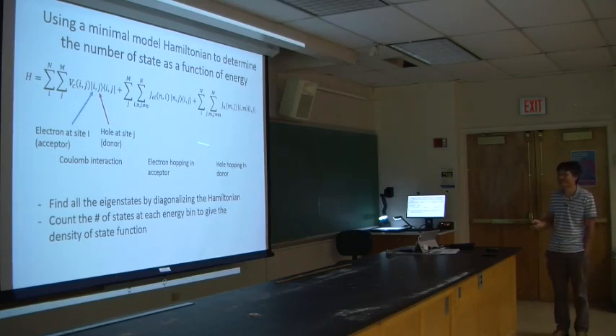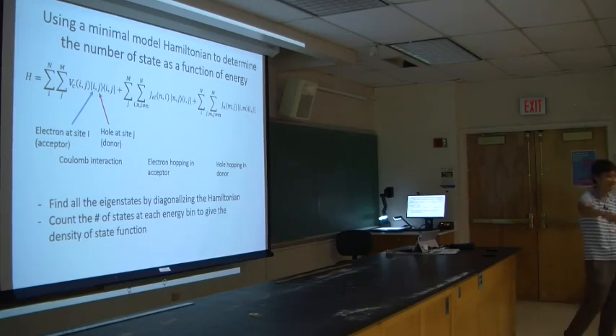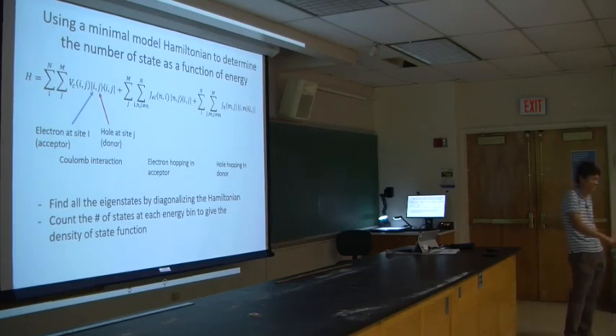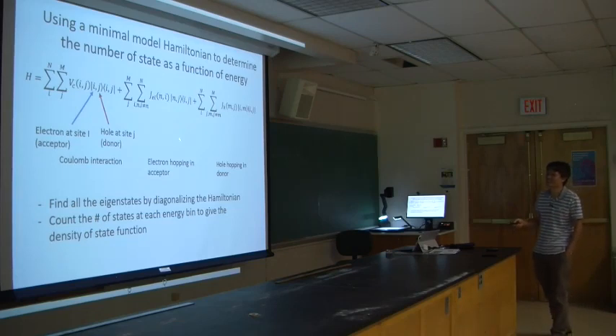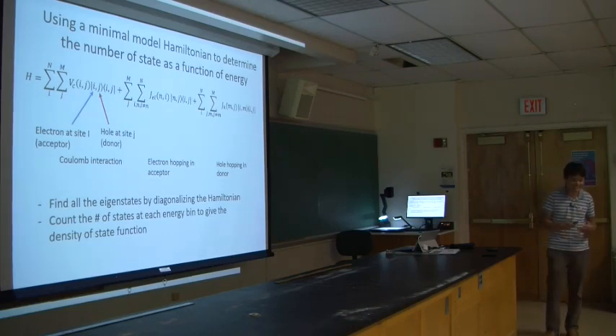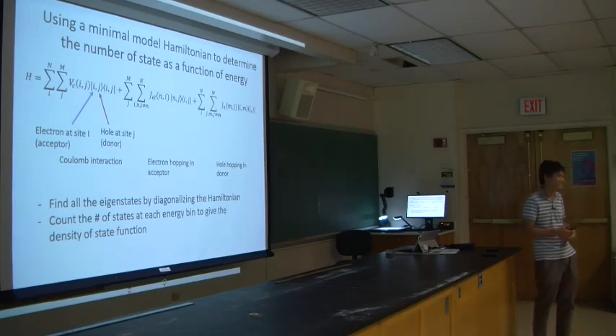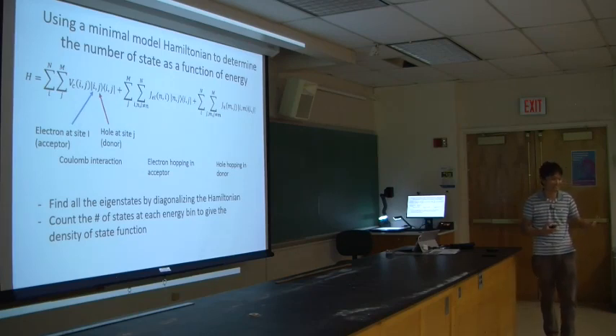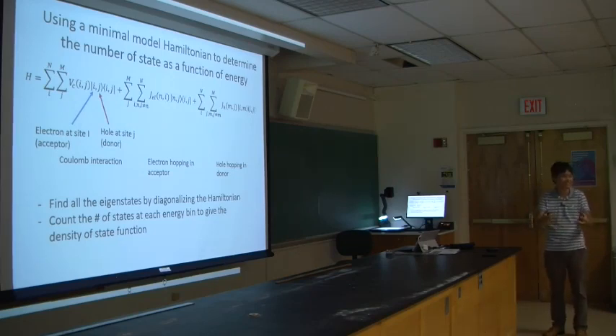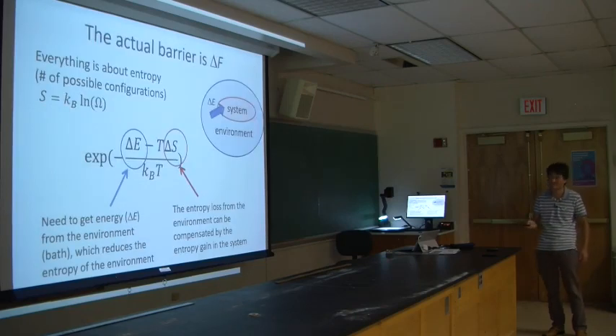So we set up this kind of model Hamiltonian. I won't go into the details, but we basically use these two electron wave functions. We assume the electron is at a certain molecule in the acceptor and the hole is at a certain molecule of the donor. And then we have these Coulomb interaction terms, which depend on the distance between the electron and hole, right? And then we have these electron hoppings in the acceptor and the hole hoppings in the donor. So we can write down this Hamiltonian and diagonalize it to get all the eigenenergies and eigenstates, right? Then we can count the number of states in each of these energy bins and basically find the omega in the entropy function, right?